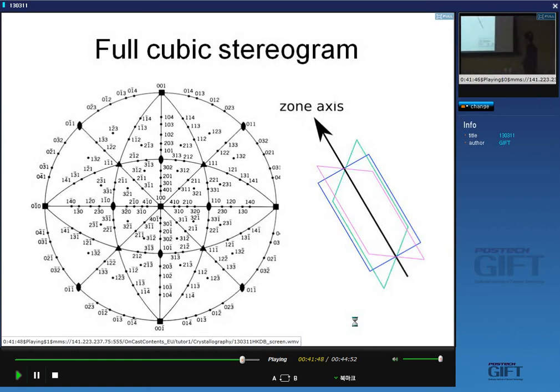When there is a direction which is shared by many different planes, okay, so you've got a single direction with many planes intersecting along that direction, that's called a zone axis. So if your electron beam is coming down like this and you've got a diffraction pattern with spots on that pattern, then all those spots represent normals to planes. So all those planes belong to the same zone, whatever the direction of your electron beam is. Okay? So the normal to a diffraction pattern is called a zone axis, because it lies at 90 degrees to all the plane normals contributing to that electron diffraction pattern. Okay? So that's a zone axis.